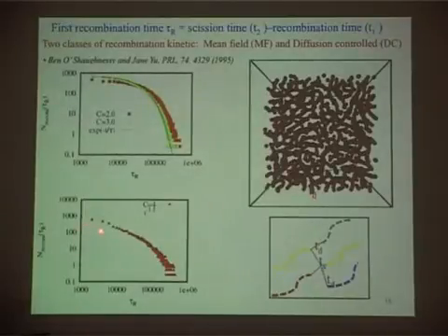And so this is at low concentrations where you have exponential recombination time. Okay, and at high concentrations you have a power law. Now the difference between these two is that here it's mean field like. Okay, so you have a scission happening, and then it has equal probability to combine with any other micelle. While here you have a scission happening, it has a higher probability to combine with itself again. So that's what leads to the power law in this case.